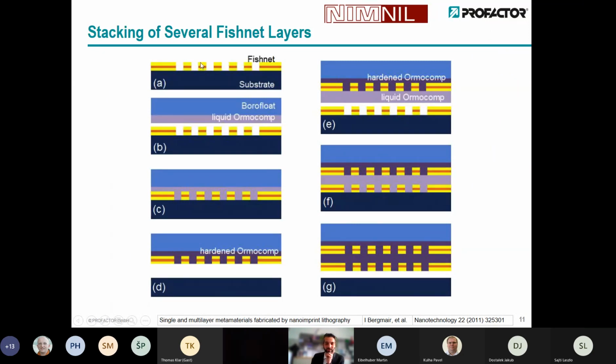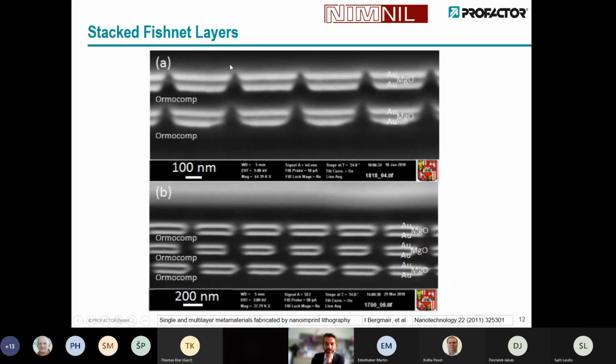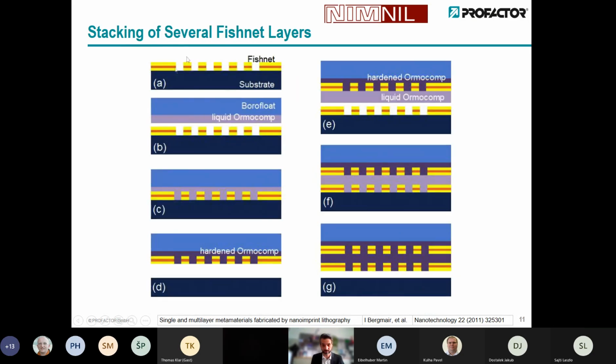And if you have such a structure, multi-layer on the substrate, you can remove it from the substrate. And this was done by embedding it into liquid Ormocomp material, which was coated on glass wafer. It is cured, and when it is removed again from the substrate, this structured material stays within the Ormocomp. And you can do this several times, and using this process, create a multi-layer of those negative index material stacks. And this is what it looks like in the end. So you have those multi-layers which are deposited in one go, and then they are stacked on top of each other. And the advantage of such a process is that you do the whole single layer processing on a simple substrate, and then you can add, if it works, on top of your already multi-layer stack you have already processed.